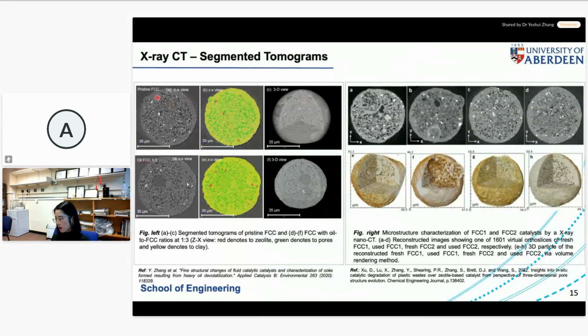If you look at, for example, figure A on the left here, that is a cross-section of this single FCC catalyst particle. Instead of looking at the surface, we look at the cross-section. We can even reconstruct the 3D structure of this single catalyst particle and do the analysis. We have published two pieces of work using this X-ray nano-CT to see the internal structure evolution of this FCC catalyst particle. The right-hand side is another piece of work.